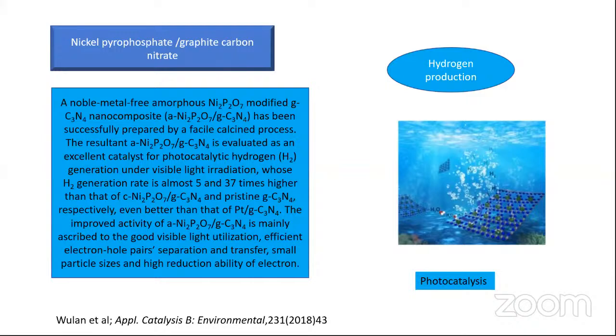The resultant nickel pyrophosphate graphitic carbon nitride is evaluated as an excellent catalyst for photocatalytic hydrogen generation under visible light irradiation, whose hydrogen generation is almost 5 and 37 times higher than the earlier reported one. So this is a very useful photocatalytic reaction to produce hydrogen.